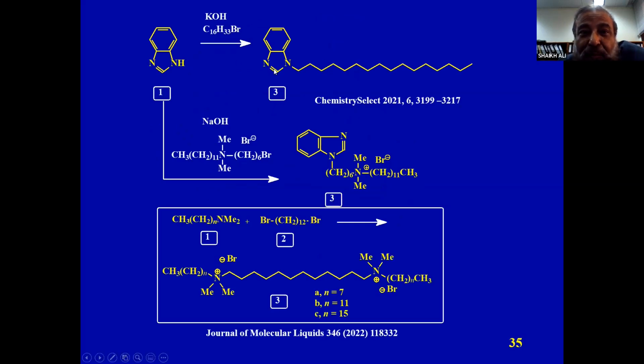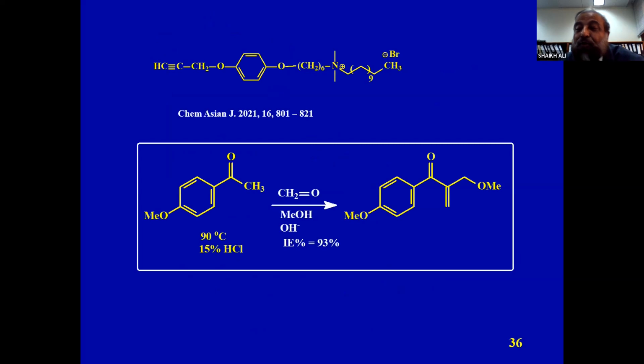And there are other groups of compounds containing benzimidazole, and here benzimidazole, another quaternary group that will impart water solubility. These are for 15% HCl, that oil reservoir, when they treat them to clean the reservoir, and then you have to protect the mild steel at 15% HCl. This is one of our best compounds, we filed for patent, that at 90 degrees centigrade, 15% HCl is giving inhibition efficiency of 93%. This molecule is so superb.